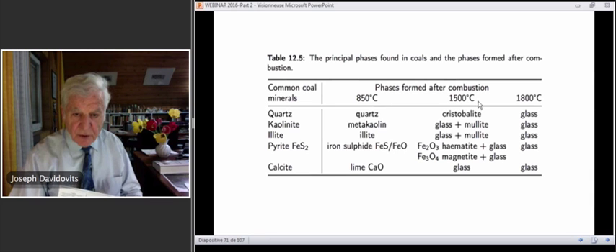Combustion at 1500 degrees C, the quartz transforms into cristobalite, kaolinite into glass plus mullite, illite into glass plus mullite, and the iron sulfide is transformed into iron oxide, hematite, plus glass, and the calcite into glass. And at 1800 degrees C, glass, glass, glass, glass. But you have also sometimes the fly ash that is made in between.